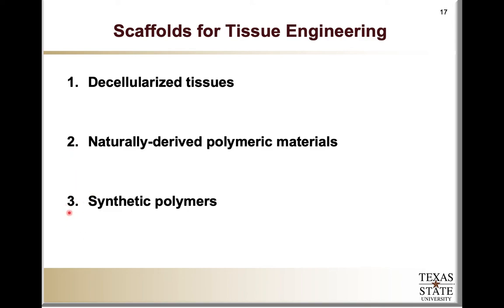Number three would be synthetic polymer systems — typically hydrogels or hybrid materials. They have good mechanical properties that resemble those of soft tissues, basically able to take 1 to 10 kilopascals in terms of mechanical stresses. They are highly porous, which is good for effective mass transport. They can be easily synthesized through a number of mild processes, such as free radical polymerization initiated by UV, thermal, or redox initiators. We can also prepare hydrogels by ionic gelation or by orthogonal chemistries such as click chemistry. These hydrogels are also easy to functionalize to provide bioactivity and growth factor delivery, either by covalent attachment of biomolecules or by entrapment within the cross-linked polymer network.